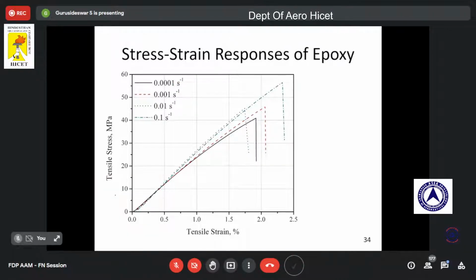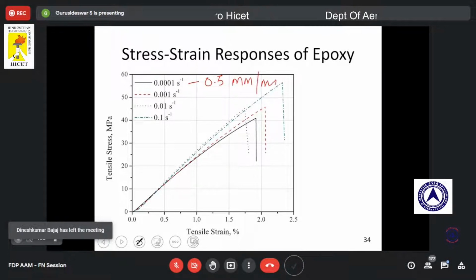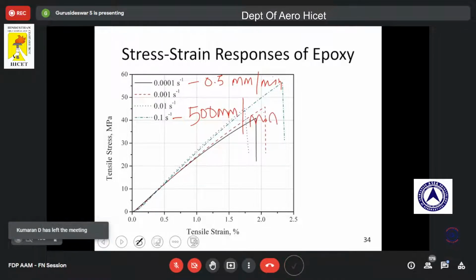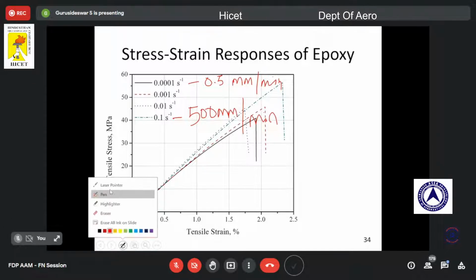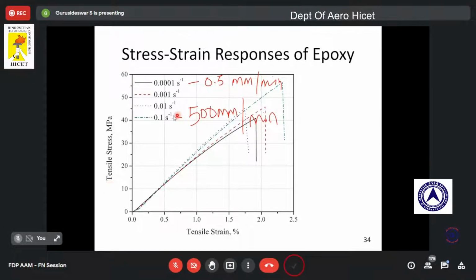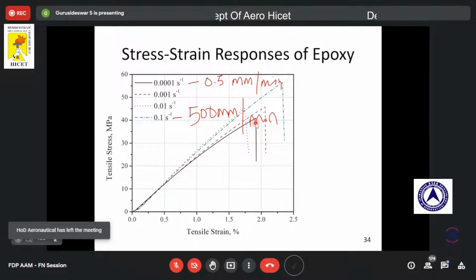Maybe I can use the pen. So this corresponds to 0.5 mm per minute, wherein this 0.1 corresponds to 500 mm per minute. So we have taken 4 different strain rates, that is 4 different crosshead speeds, and we wanted to understand its behavior. So you can see at the lowest strain rate, 0.0001 per second, for neat epoxy the strength is around 40 megapascal.